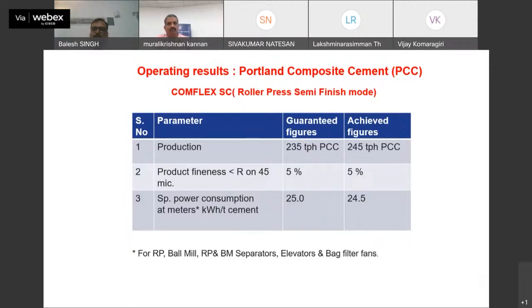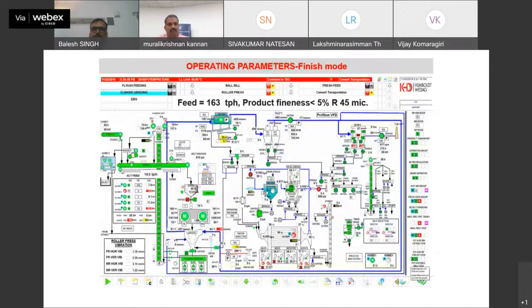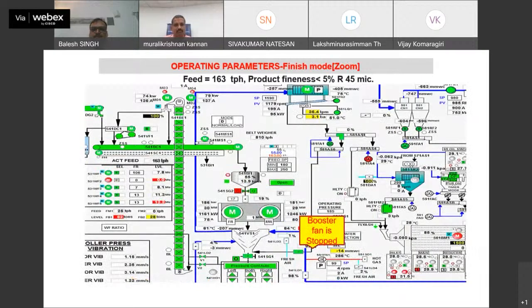And when it runs with composite cement, the production was 245 TPH with less than 5% residue, and the total power was 24.5. This is the real screenshot of operation of roll press in finish mode, where we can see 163 TPH, and this is for semi-finished mode when it is working with ball mill.